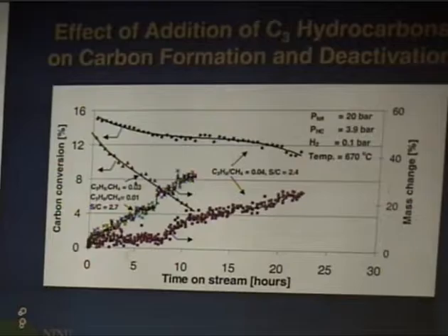Here we have the carbon conversion as a function of time on stream. And here we have the mass change as determined by the thermobalance reactor. In this case, you can see we have a small deactivation. So that depends on carbon formation. These experiments are done at 20 bar